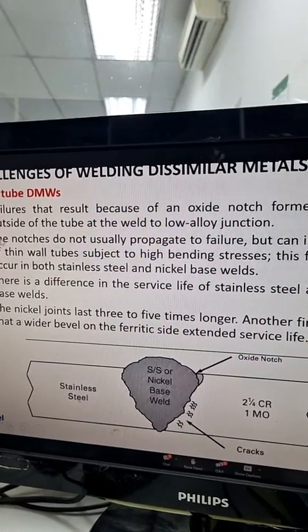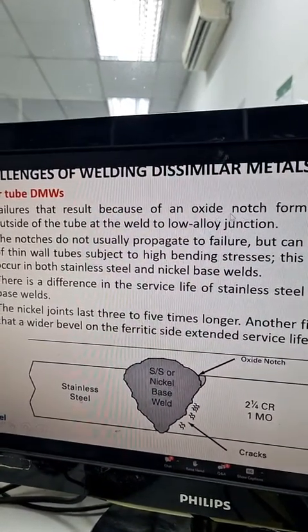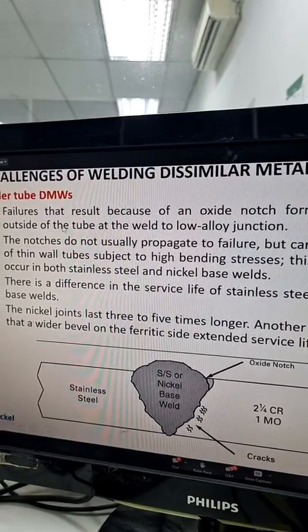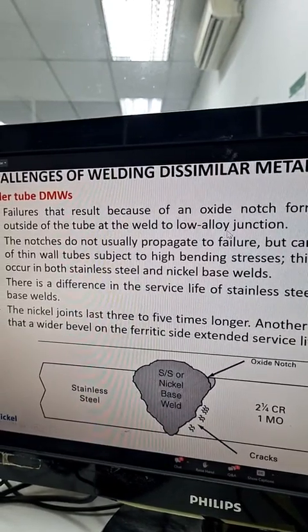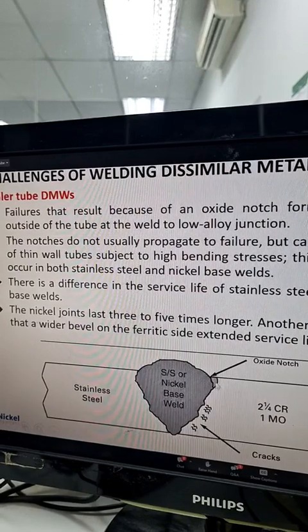Another type of failure was attributed to the oxide notch formed on the outside of the tube at the weld to low alloy junction. You can see here an oxide notch. The notches generally do not propagate to failure, but can, in the case of a thin wall tube subject to high bending stresses, initiate a failure.